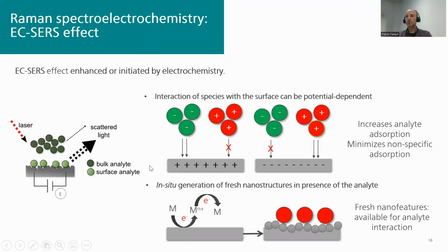So how is the integration of this electrochemistry with the SERS effect? Well, usually working with a metallic electrode, we have two approaches to promote this SERS effect. So the easiest one is just to polarize the surface of our electrode. So we can apply a positive or a negative potential, and we can force some electrostatic interaction with analytes that are negatively or positively charged in our solution. So we can modulate and increase the adsorption or the interaction of a specific molecule with the surface of the electrode. And usually the second approach to generate this SERS substrate in our metallic electrodes is to do some electrochemical pretreatment. So to get some increased roughness in the surface of the electrode, or even to get some nanostructures that will interact with the analyte in the solution and will provide this SERS effect.